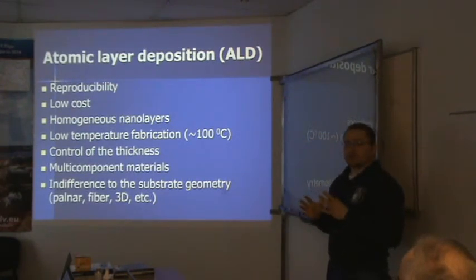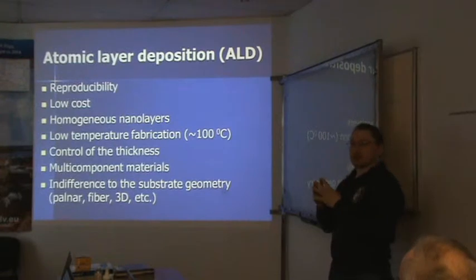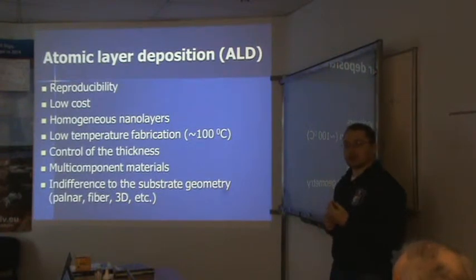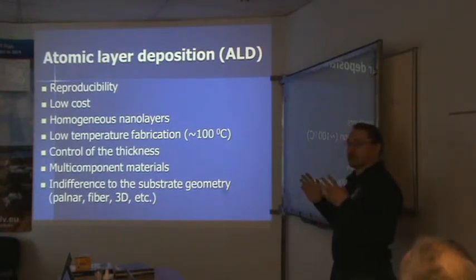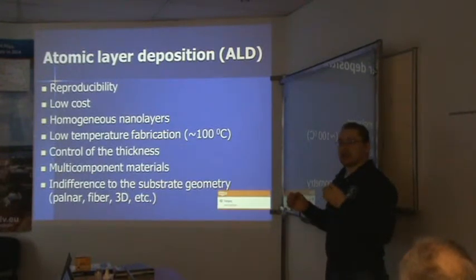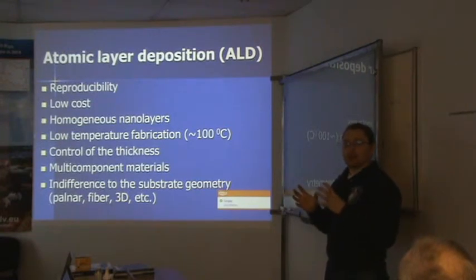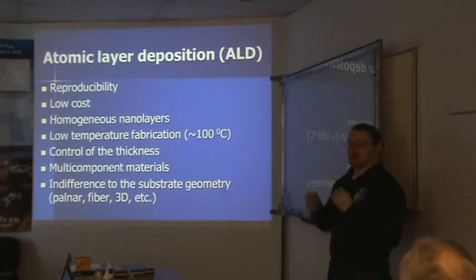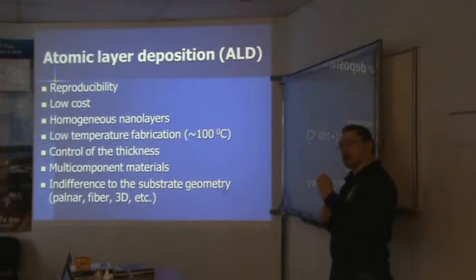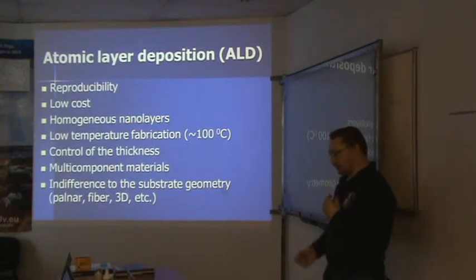For deposition of these materials, we started collaboration with the University of Montpellier. They are chemists and we are physicists, so we put together two expertises and we managed to make metal oxide nanostructures deposited by atomic layer deposition. The advantage of this method is that it can be used for different purposes. You can grow thin film layers, you can coat different surfaces, and it does not matter which kind of geometry of the substrate you want to coat. So you will have a conformal and uniform coating, and you will control the thickness and the chemical composition of the coating you deposit on the substrate.